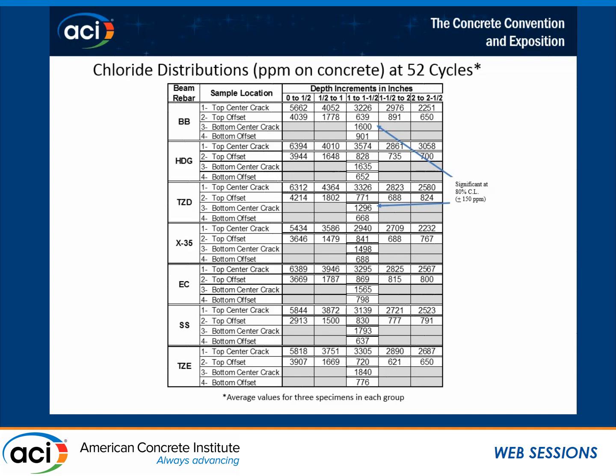Looking at the bottom center, where the crack didn't get that far down, it's got almost 1.5 to 2 times the amount of chloride that's away from it.